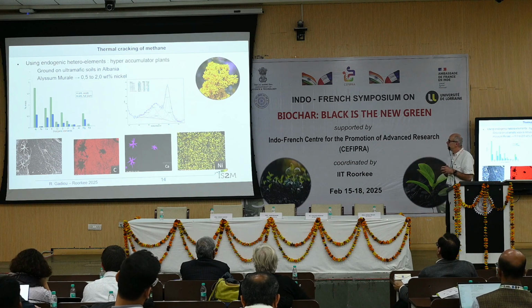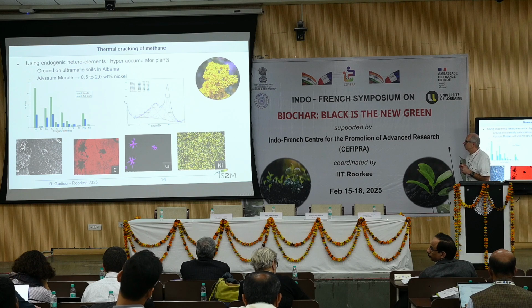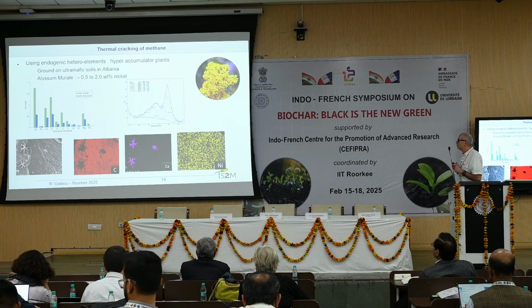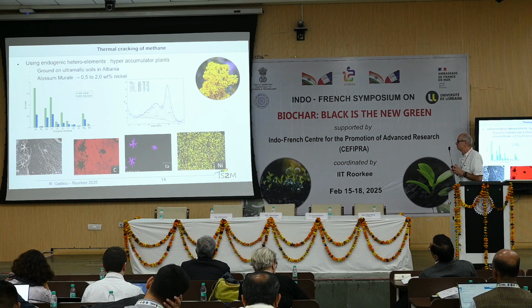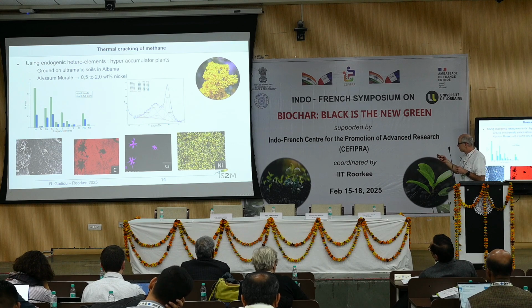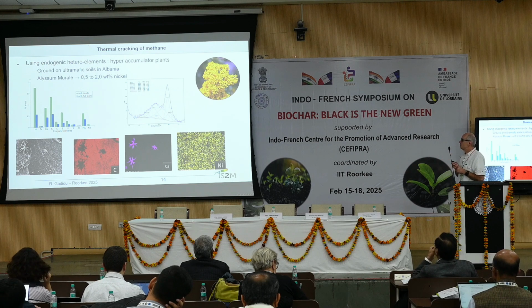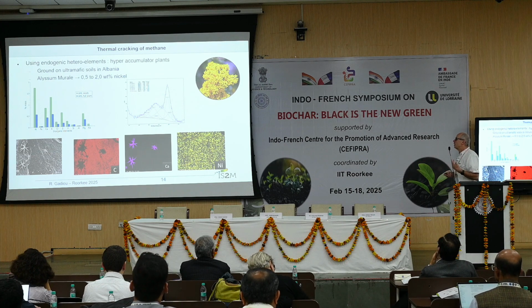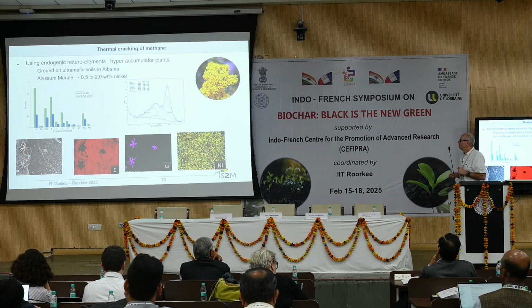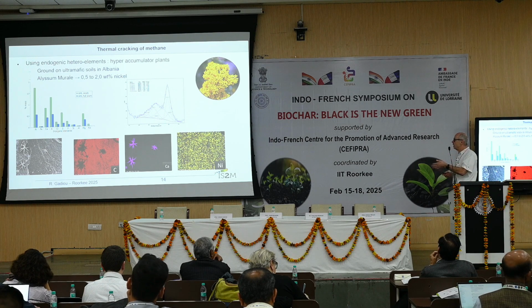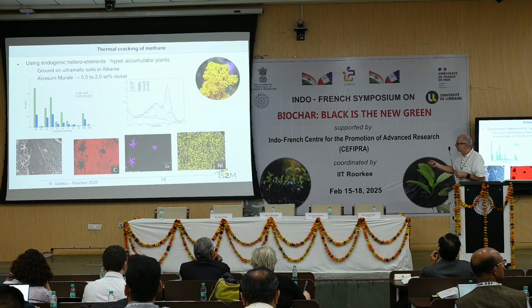So you have the chemical analysis showing the amount of nickel. You see the seed and the full plant are different. So we have worked with the full plant because it had no sense from an industrial point of view to work only on the seed. An important aspect is that the speciation of nickel is of importance. So of course, when you use some XPS analysis, we see that we have nearly all which is present as nickel 2+, either in the form of oxide and different other compounds.